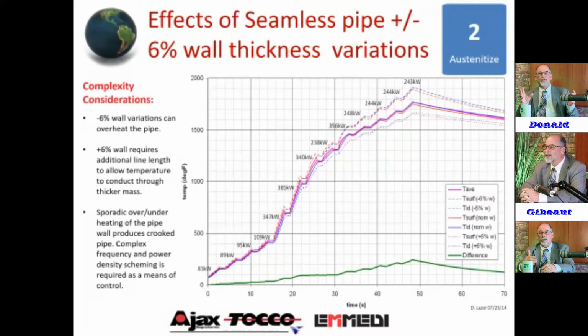So, where most of the surface heat is below the magnetic Curie point, the algorithm that we came up with together through this development came out to reducing the power density below the magnetic Curie. Below the magnetic Curie, we slow it down there and then pour the coals to it when it's above the magnetic Curie, where that depth of penetration is 4.5 times deeper.